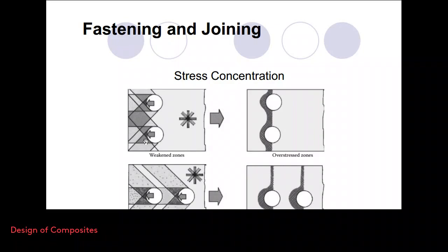So we see that these regions are weaker in this configuration if you put the holes side by side, and as a result you see a high stress value around the holes. If you put one hole in front of the other, then you see higher stress value in front of the hole, which comes from the joint. It's a pin, it's a rivet, or whatever it is.